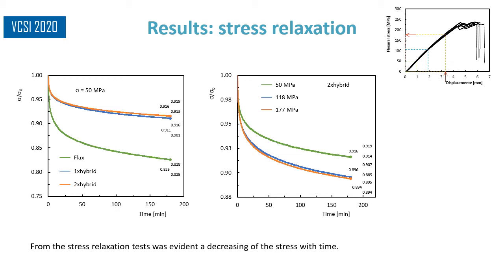Besides the average values obtained after 180 minutes, shown by closed round symbols, the figure also shows the respective maximum and minimum values for each condition. Similarly, for the 2x hybrid laminate, the strain values used were 0.28%, 0.82% and 1.46%, and 180 minute tests were performed, and the stress is recorded as a function of time.